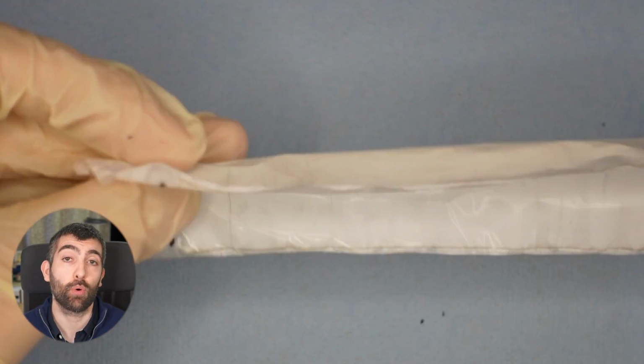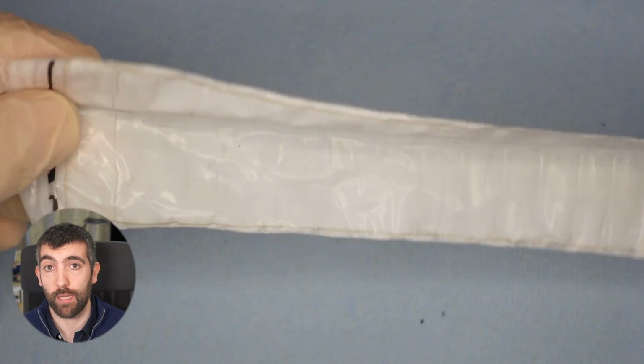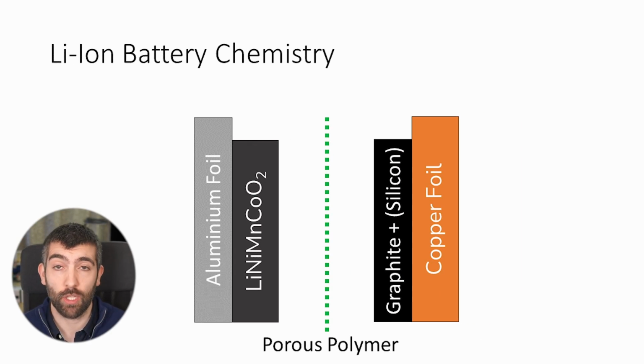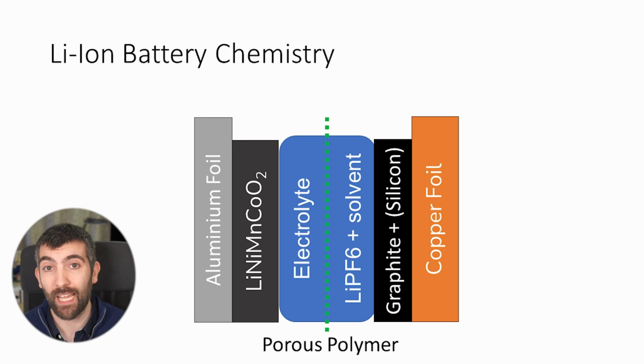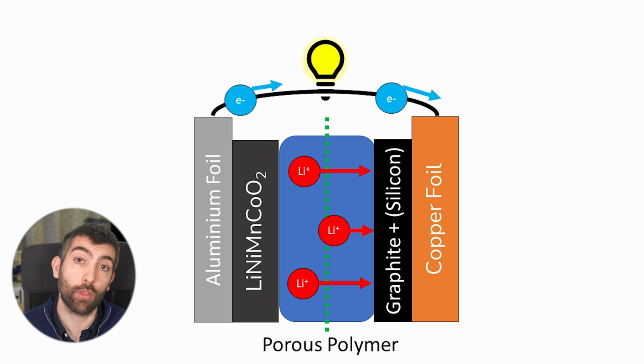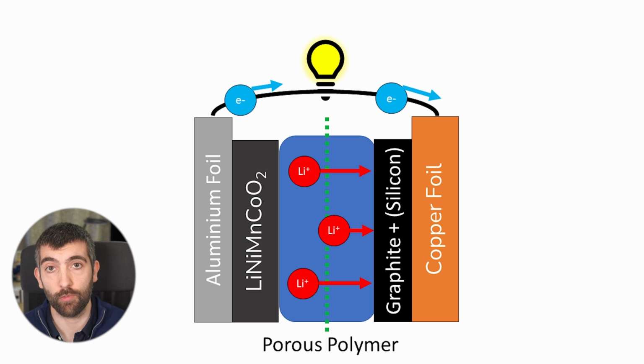Between the 2 sheets is a porous polymer film soaked in a liquid electrolyte. And that liquid is normally a lithium salt, so lithium hexafluorophosphate, dissolved in an organic solvent. And that electrolyte is there to allow the lithium ions from the cathode, from the aluminium foil side, to flow easily to the anode. While that's happening, electrons will flow through the electrical circuit connected to the battery, and they'll also flow from the anode, the aluminium foil side, to the cathode, the copper foil side. And we can use those electrons flowing to generate light, to drive motors, anything that requires electrical power.